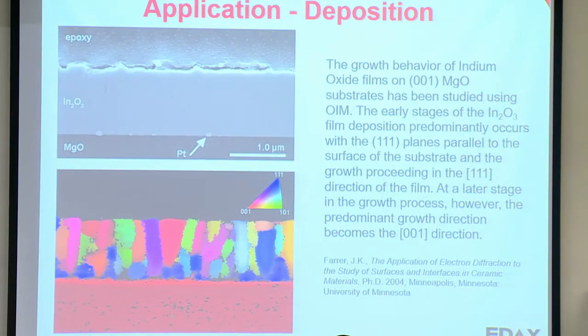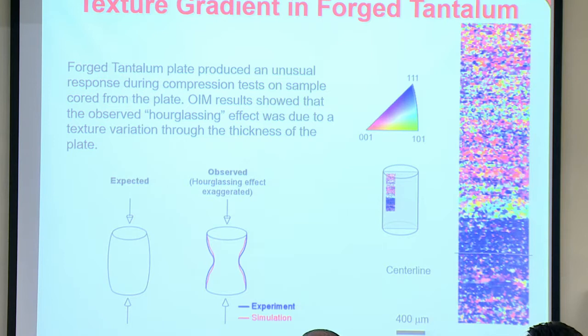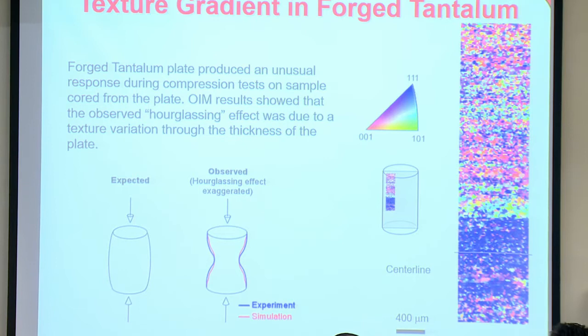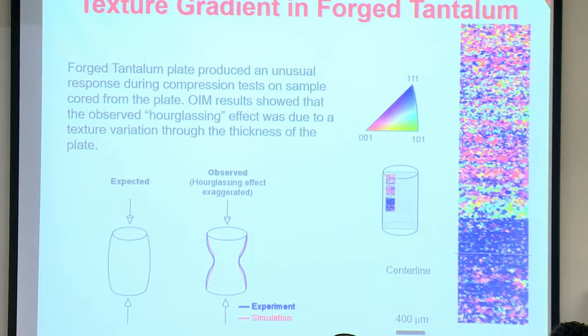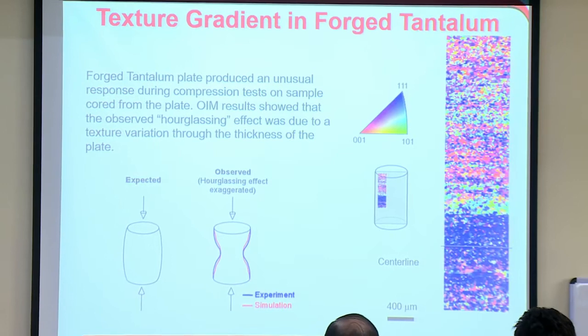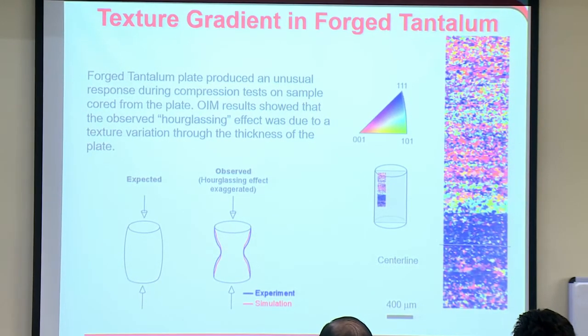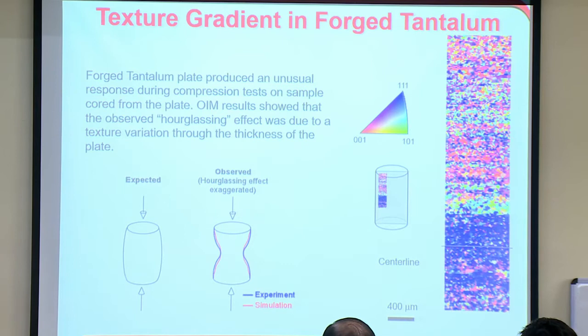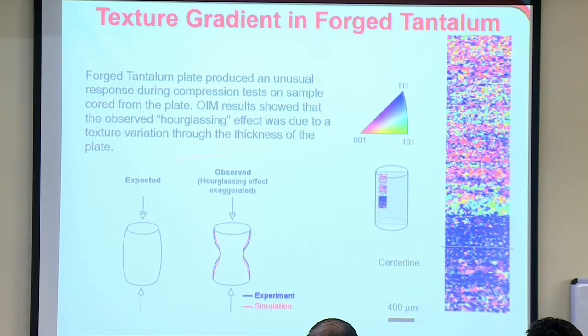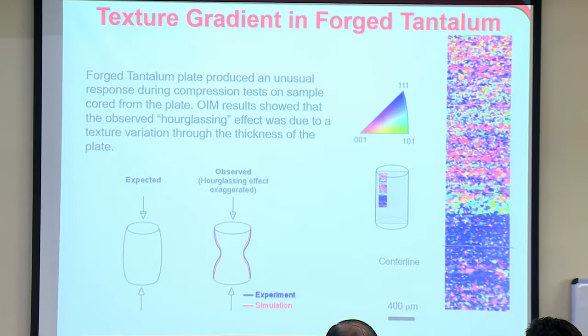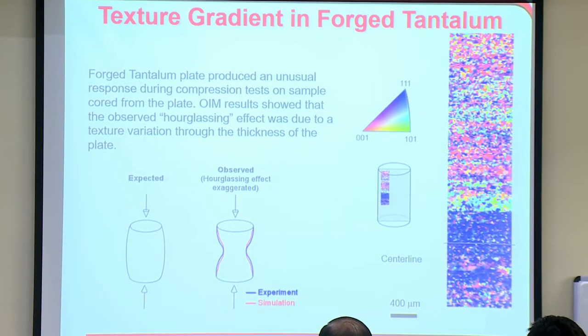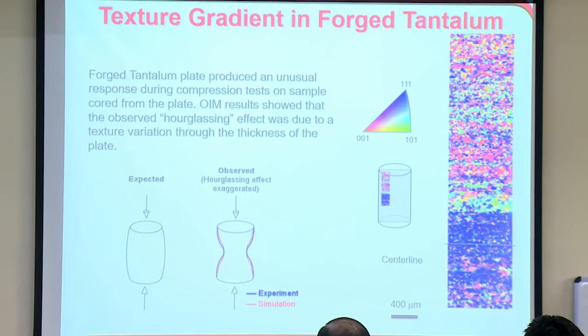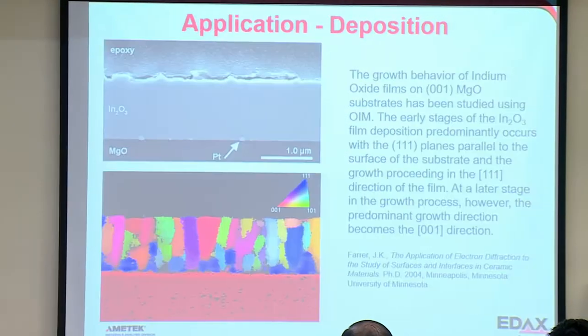So I want to go through quite several applications here just to show you what EBSD can do. We did a little study looking at all the journals and all the EBSD papers, and we found overwhelmingly that these kinds of deformation ideas are the number one use of EBSD. Probably around 60 to 70% of the papers out there are dealing with deformation and strain. It's interesting because this is one of the very first things I did, and that's continued to be the use of EBSD. This was more of an engineering example than material science, really, but it just shows what can be done.